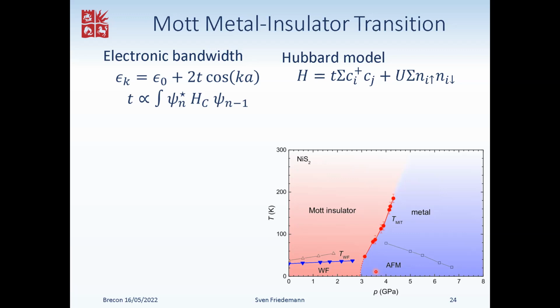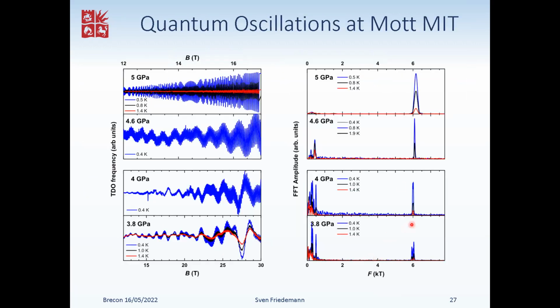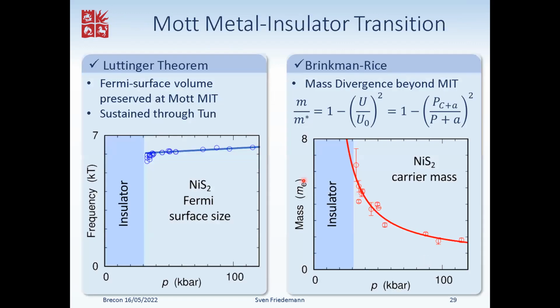I don't know. So what is the logic now of Luttinger's theorem? We are comparing what with what? Just for me to understand. What I'll be looking at is whether or not the Fermi surface on the approach of the metal-insulator transition remains the same. I see. Okay. And that is already to some extent visible here, in that the high frequency remains. If we look at this in more detail, the frequency in fact only depends very weakly on pressure, and this solid line that I've put through here is exactly what you expect based on the compression of the material. So it tells us that the Fermi surface does remain large right up to the insulator transition.